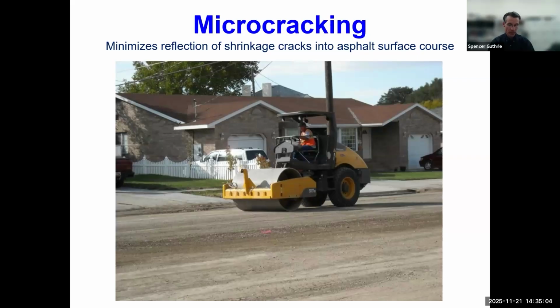Okay, those are great questions. Thank you. First of all, regarding microcracking, what we find is that in general, asphalt pavements are thinner than concrete pavements for residential roads in particular. As we move to higher trafficked roads, the thicknesses approach being similar. But we also know that the concrete has a stiffness, a Young's modulus, of around 4 million psi, whereas asphalt is around 400,000. So concrete is 10 times stiffer. Being generally thicker and stiffer, we have not yet documented the occurrence of reflection cracking from an underlying cement-treated base in a concrete surface layer, whereas we frequently see it in asphalt. So the absence of the occurrence of the reflection cracking leads us to have this policy where we can omit microcracking when concrete pavement will be placed. Is that okay for that question?